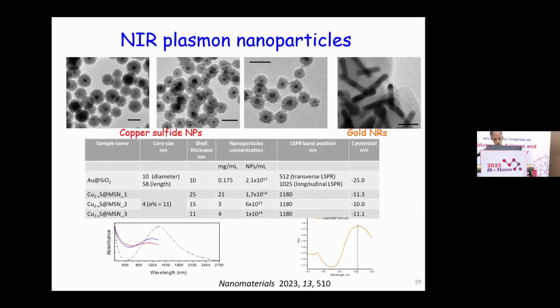So in this work, we used different nanoparticles in order to realize the enhancement of anti-Stokes emission. Particularly, we used copper sulfide nanoparticles covered with a mesoporous silica shell of different thickness. And also we used gold nanorods, also covered with mesoporous silica. Mesoporous silica is necessary in order to prevent direct contact of the molecule and the plasmonic nanoparticle, because direct contact results only in the quenching of photoluminescence. We need specific separation between the nanoparticle core and the luminescent molecule.